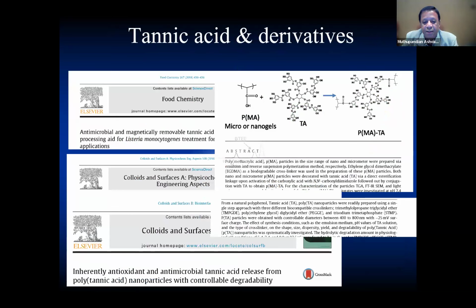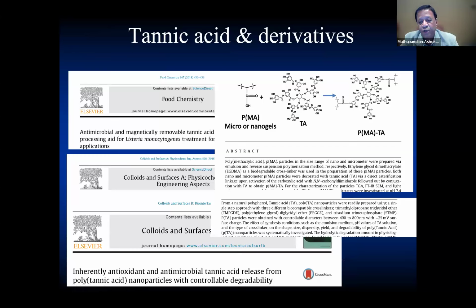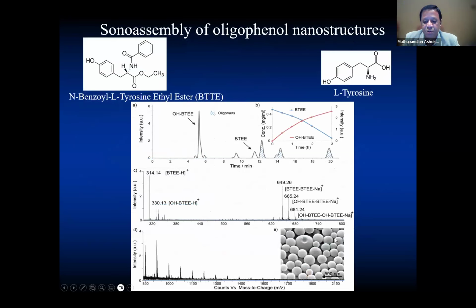So what we can use here is we can take some simple molecules which are biofunctional and convert them into nanoparticles. What the literature shows is that if you take, for example, tannic acid, which is basically a polymer or polyphenol molecule, it has very high antioxidant capacity. But if you just take tannic acid or any other polyphenolic molecules as they are, like they're there in all fruits and vegetables, they're not staying in the stomach long enough for them to be absorbed. And what the studies are focusing on now is that if you convert these molecules into nanoparticles, then the nanoparticles can stay in the stomach for a much longer time, slowly releasing the polyphenolic molecules into our system that has a proper